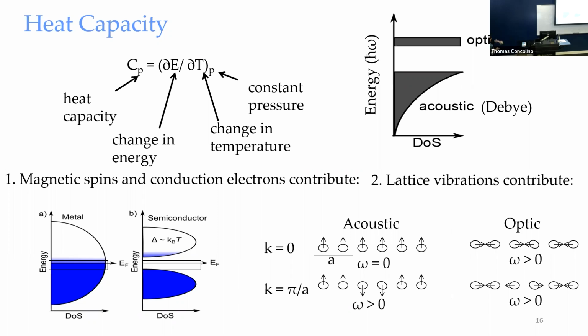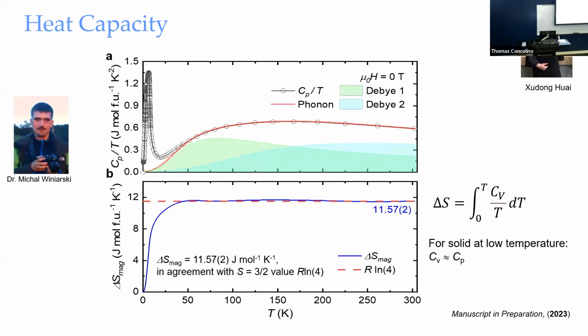So acoustic phonon, okay, sorry, I'm running out of time. So here is the heat capacity data. A friend of mine in Poland helped us measure the data. Heat capacity. So what you see here, the anomaly in heat capacity at around 10 Kelvin, is consistent with what we see in magnetization. And the phonon contribution here can be described by a two Debye modes.